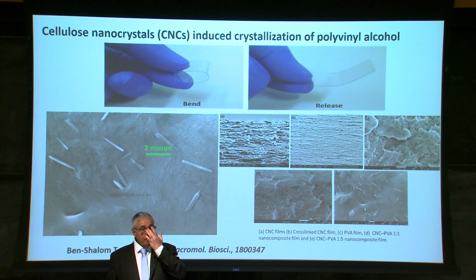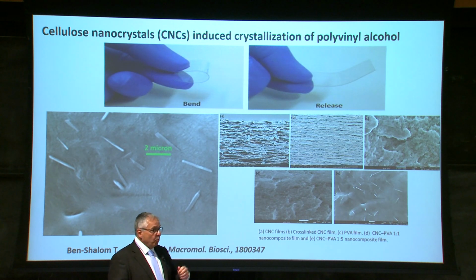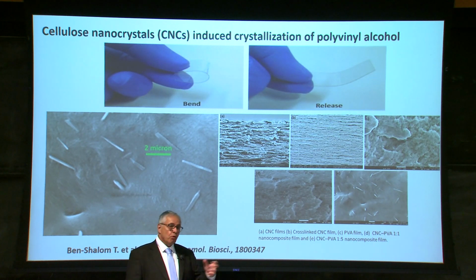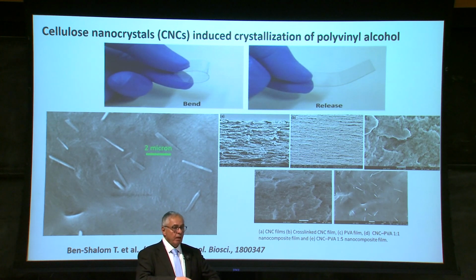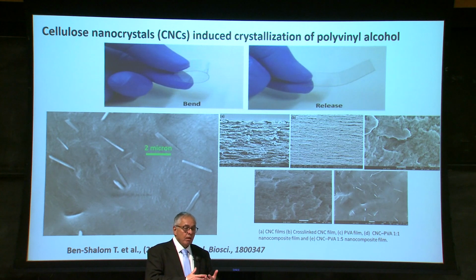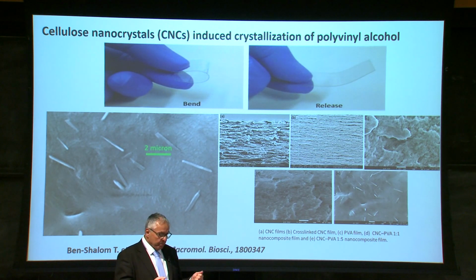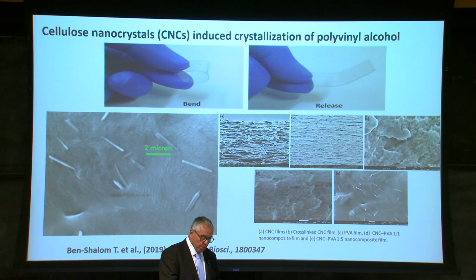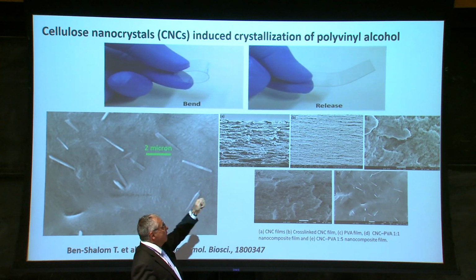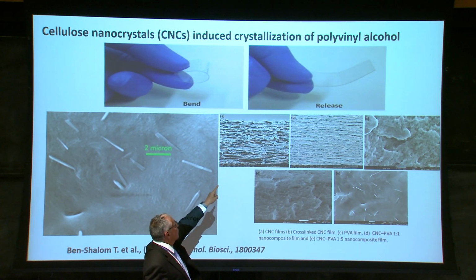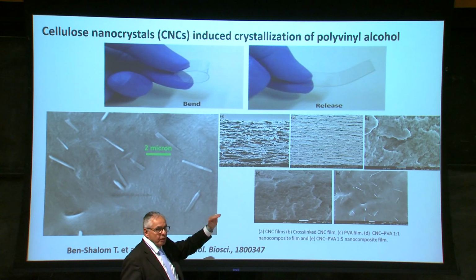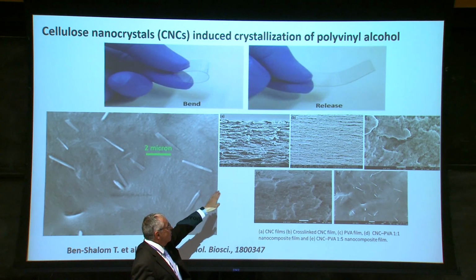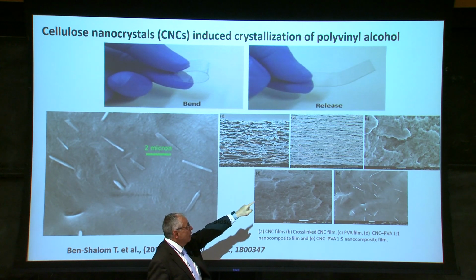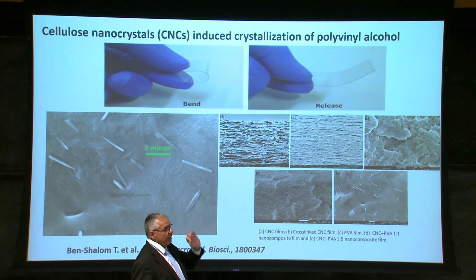Another interesting feature of cellulose nanocrystal was achieved when we mixed it with another interesting polymer, which is polyvinyl alcohol, PVOH. And it turns out that if you mix it in water and then you dry it, it forms a very, very strong film that you can see here at the top. You can see here that it's quite transparent and also flexible. But what is more interesting is that here on the left or in the middle, the A panel, this is a cellulose nanocrystals cross-section without cross-linking. This is cellulose nanocrystals after cross-linking. And here on the right-hand side, this is just polyvinyl alcohol.